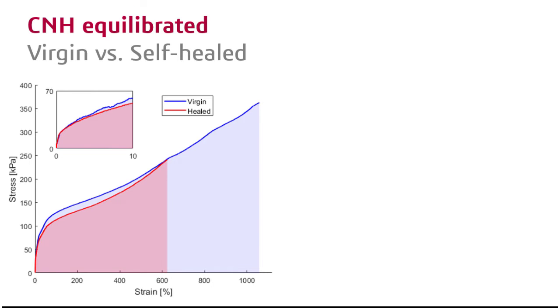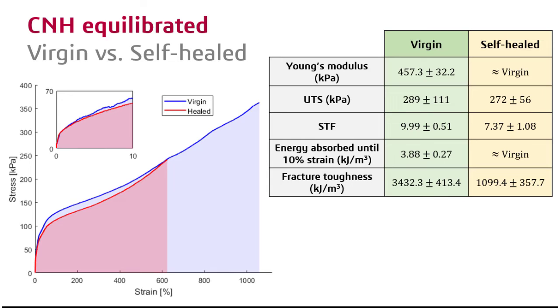In this graph, we show the tensile stress strain curve for a virgin specimen in blue and a healed one in red. It can be seen that the performance of the healed specimen is approximately equal to that of the virgin until the failure, which is the major difference between the two cases. The numerical results can be seen in this table.